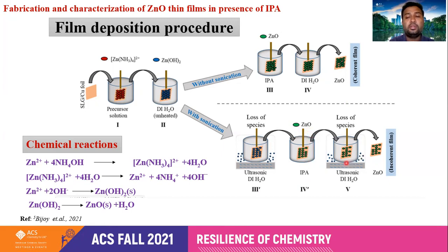And again, I dipped into the ultrasonic deionized water. In that case, a great portion of molecules which are loosely attached on the substrate surface are removed, and the quality of the zinc oxide thin films is not good. For that reason, I eliminate the ultrasonic deionized water step in case of without sonication procedure.